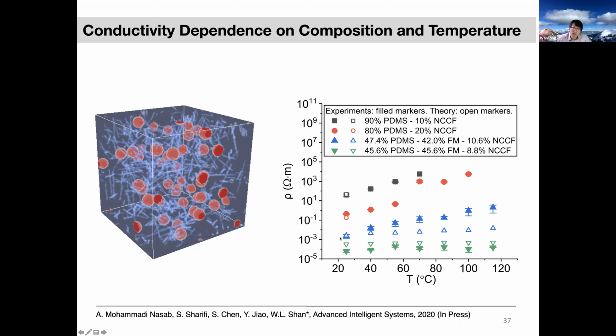But we can see in the experiments for this other three-component composite, the electrical resistivity actually changed a lot when we increased the temperature. So we figured that we might be sitting at the percolation threshold when we play with the volume fraction. Clearly, there's a lot to investigate here, and we are trying to do that together.